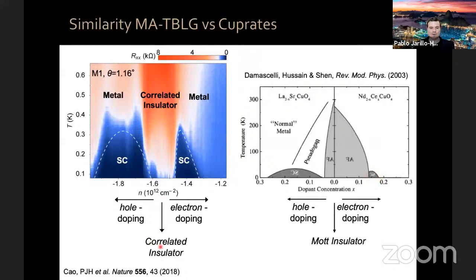Here we have a 2 holes per moiré unit cell correlated insulator. We add holes, we have a superconducting dome. We add electrons, we have another superconducting dome. Now, of course, there are many differences between these two, there are only some analogies, other things are very different. An important difference is that this is a theoretical phase diagram. In order to make this phase diagram experimentally, you have to grow a different material, different chemical composition, often different material classes as you populate this doping concentration.